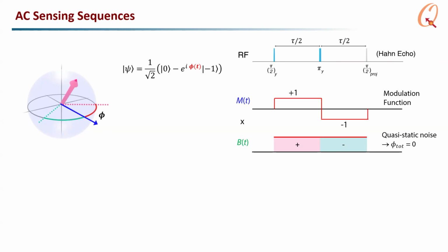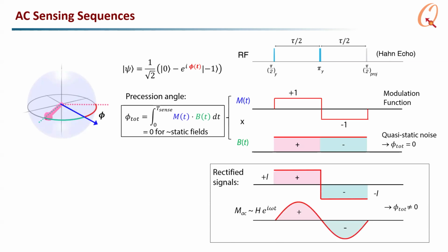So if you had a static magnetic field, you see that the precession angle at the end of the Hahn echo is 0. The work that you did in the first half of the precession got negated, and then you catch back up in the second half. So that's 0. However, if you can control your signal, by changing the sign of the current, or maybe inducing an AC magnetic oscillation, then you can rectify that signal. Essentially, the phase that you get is the modulation function, which switches sign at every pi pulse, multiplied by the magnetic field. So if the magnetic field also switches sign, then you can measure a non-zero phase.